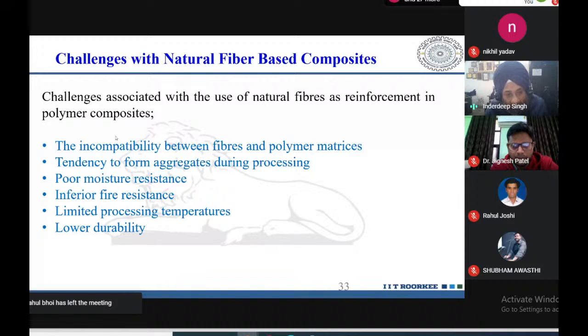Another problem while processing is the tendency to form aggregates. Once you are making the composite materials, there is a tendency that the fibers, because of the different surface characteristics, tend to be friendly with each other rather than being friendly with the polymer. So that also is a challenge, that the fibers may try to make their own smaller group and then they do not bind well with the polymer. So we have to treat the fibers in a way that they are not able to form an aggregate or do not agglomerate in the polymer matrix.